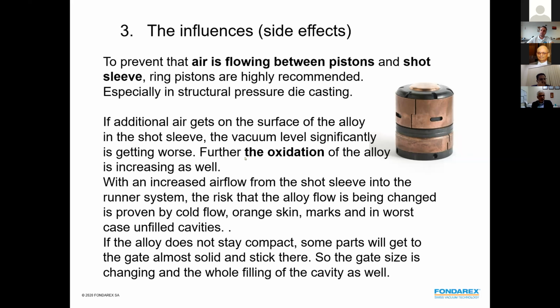The oxidation is a very critical area because if the piston is not tight, we have a higher oxygen turnover inside the die, inside the shot sleeve, and this most of the time is very bad for the quality of the casting. Another problem is if there is more air from the shot sleeve getting through the die, through the whole application.